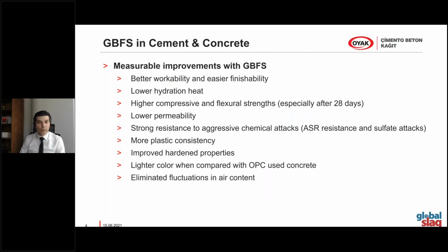When we look at GBFS, I want to quickly share some technical info. Everyone may know it, but I want to explain a little bit. We gain measurable improvements with GBFS usage: better workability, easier finishability, lower hydration heat, higher compressive strength, especially later strength after 28 days, lower permeability, strong resistance to chemical attacks, more plastic consistency, improved hardened properties, and lighter color compared with OPC. It's also important for aesthetic issues and the reflection of light. It also eliminates fluctuations in air content due to the structure of granulated blast furnace slag.